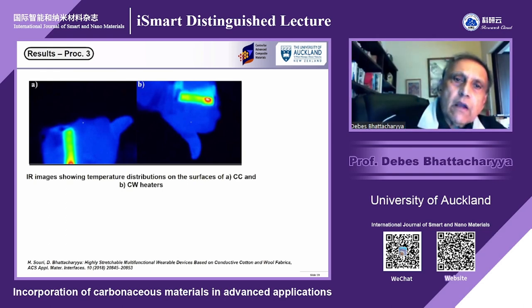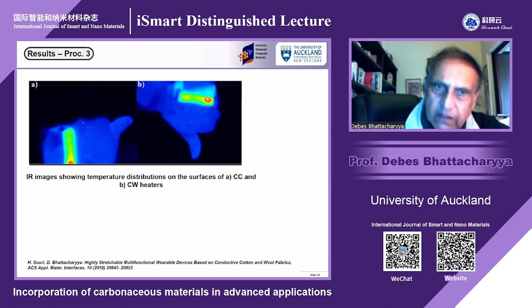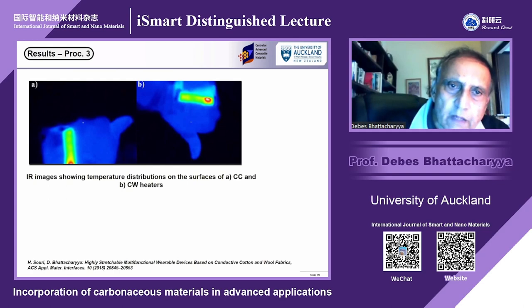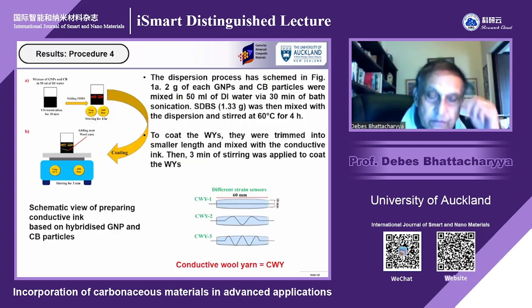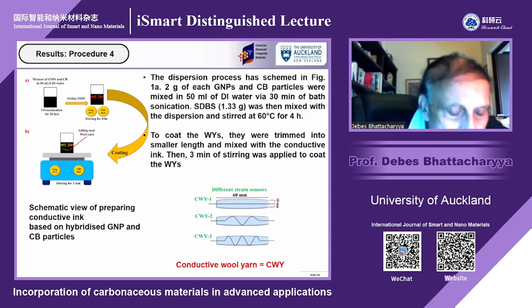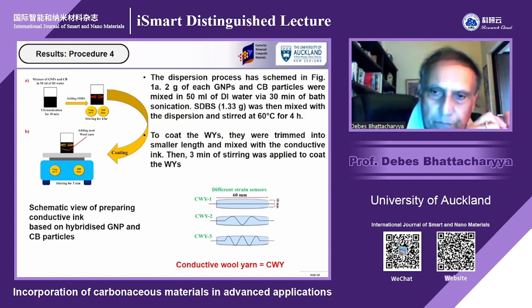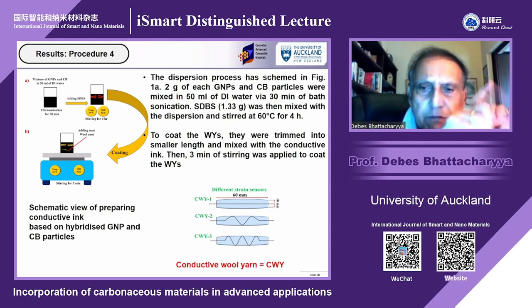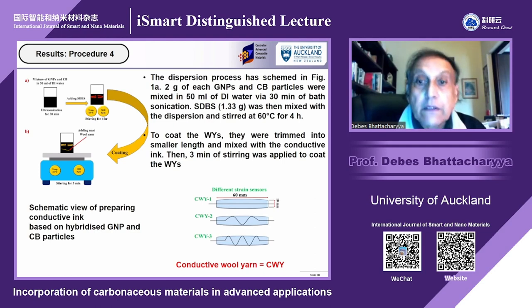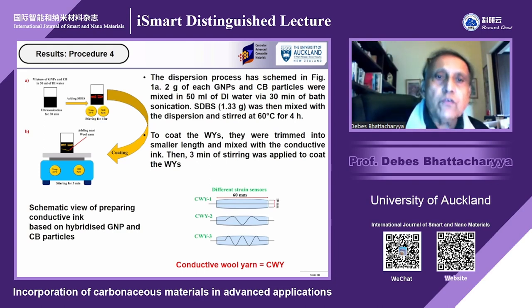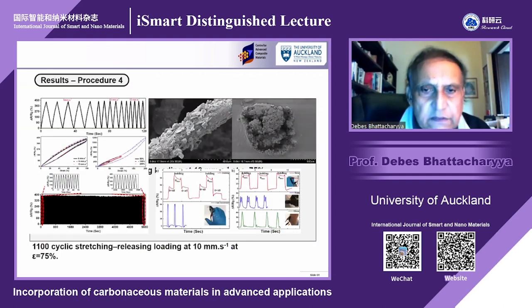So there are heat source or other things also we have established quite a bit there, all the results we established. Now, another thing we tweaked, because it is very difficult to get the fabric in a real stretch form, you will have wrinkles there. You will have those undulations. So we have CWY1, which is straight, CWY2, which has got one undulation, CWY3, which has got two undulations, followed the same process more or less, and got the results.